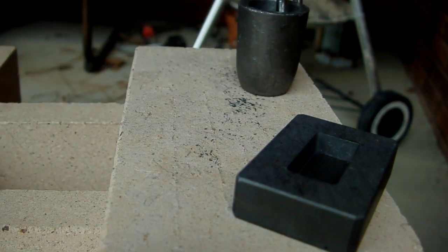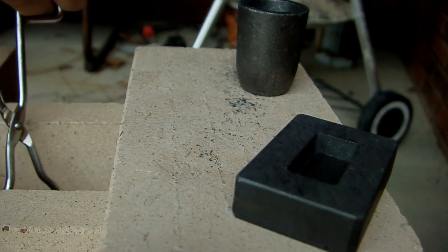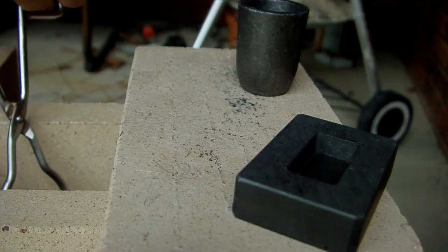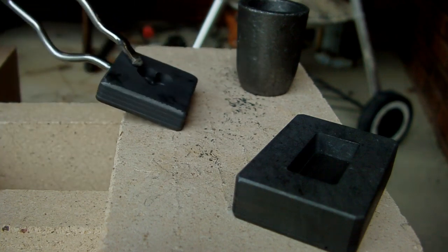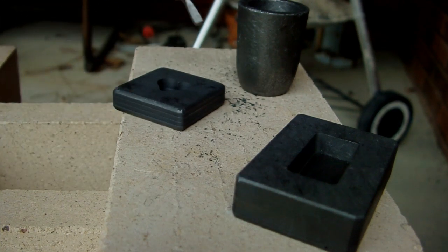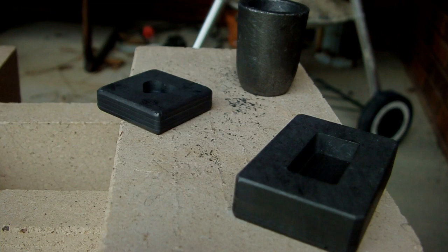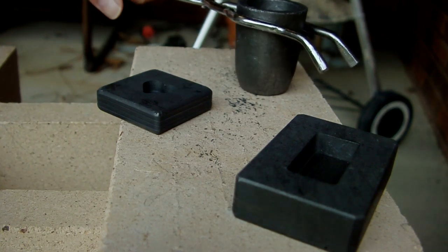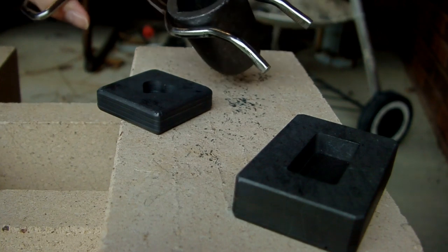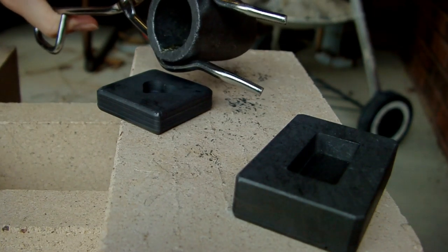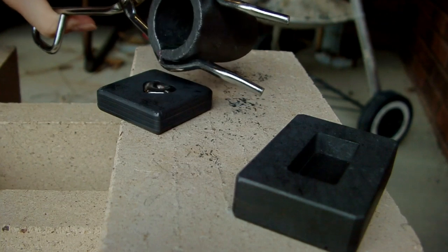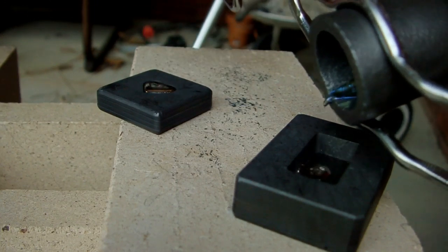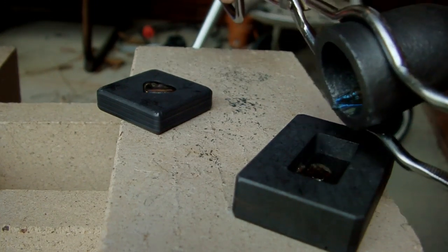So this hot surface is there to further slow cooling. I want to have as slow cooling as possible so that the bismuth has time to form nice large crystals which is what I'm looking for. So now we'll take the heart mold, get it in place and pour the molten bismuth into it. And then we'll take the excess and just pop it into the ingot mold here.